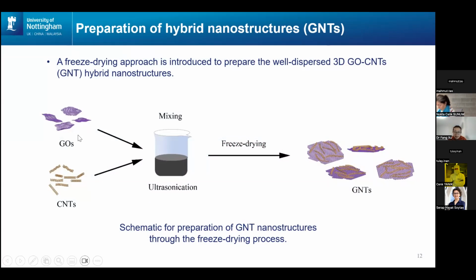What we are doing here is we choose graphene oxide rather than graphene because it's easier for graphene to be dispersed in water, and we can then reduce graphene oxide to achieve reduced graphene oxide. So we mix graphene oxide and carbon nanotube together in water using an ultrasonic probe.